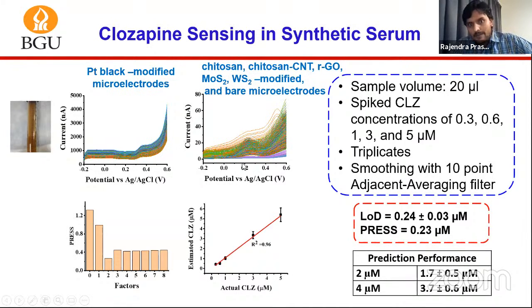error. So from this kind of linear fit, we got the limit of detection, which is 0.24, better than the single electrode, which was around 0.5 with the chitosan-CNT modified one, meaning that this kind of sensor array approach is highly sensitive. We also tested our model performance for the prediction of 2 micromolar and 4 micromolar spike samples, and we got very close values. The variation that you see is because this is a very small data set. In this kind of algorithm, basically we require a big data set.